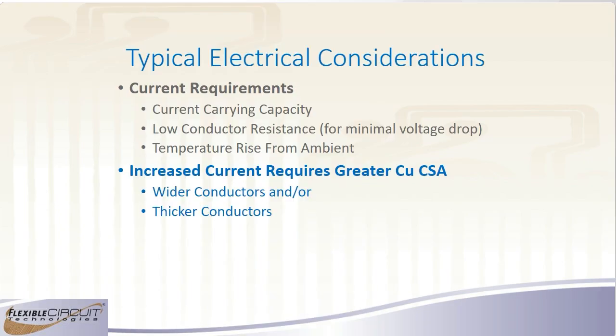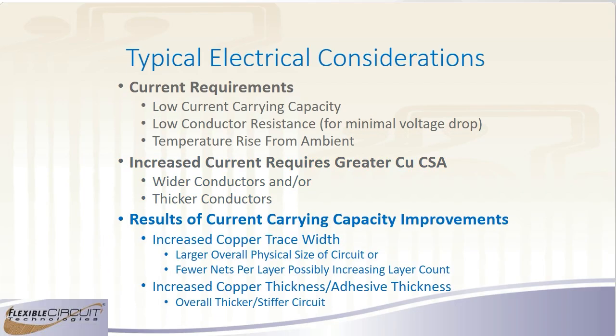Typically, there's really only two things that you have as tools to reduce your resistance in your traces, and that's your conductor width and your conductor thickness, basically the cross-sectional area, unless someone's come up with a way of making a cost-effective solid silver PCB or a superconductor that'll run at room temperature. These are really the only choices we have with copper, are either thicker or wider. And both of those can work against you when it comes to flexibility. If you have thicker traces or wider traces, they're going to take up more space on your layout. And if you are using up all of your space on a particular layer, it may drive you to additional layers. And additional layers equals additional thickness and makes your overall thickness more and makes the stiffness a lot higher.